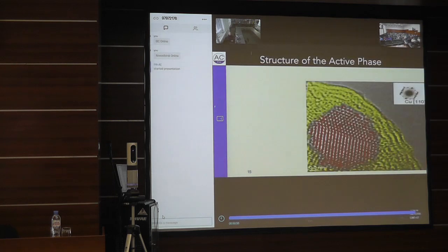Now, how does this look in nature? Here's an electron micrograph that you see of an activated catalyst. The red atoms are the copper atoms, the yellow atoms are the zinc oxide. The zinc oxide forms a very strange high energy intermediate. This is graphitic zinc oxide. You see the parallel planes. And then you see two other things that are interesting. Here, the first thing is that this small nanoparticle, that is about 3 nanometers in diameter, has lots of lattice defects. This is far away from being a single crystal.